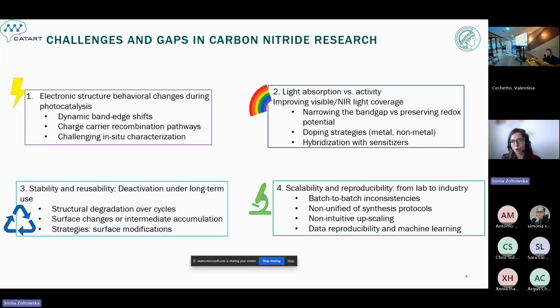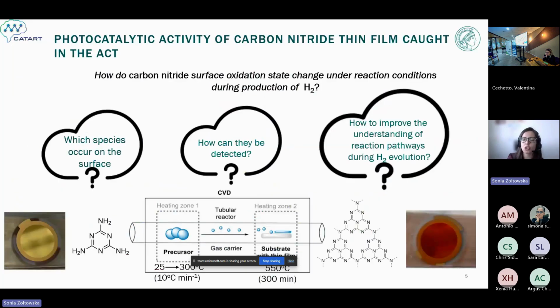And owing to those challenges, we decided, as I mentioned, to use the CVD technique to obtain the thin film of carbon nitride, to work with that in the in situ characterization during the water splitting. So on the bottom, as you can see, we prepared the film using the gold substrate, which gives us very good conductivity. We use melamine as a precursor and the classic CVD technique. So we have a two-heating-zone tubular oven, where in the first zone we put the precursor melamine, and in the second zone we put the substrate.